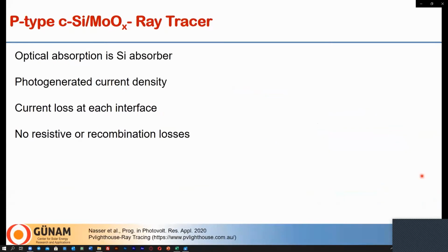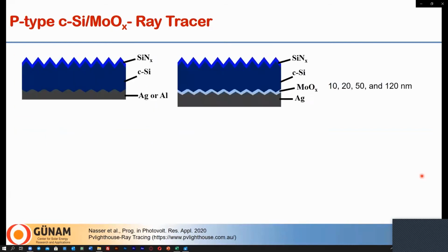So in order to further understand what happens at the rear side, we used the wafer ray tracer tool from PV Lighthouse. In this tool, it doesn't take into account any recombination or resistive losses of the layer or interfaces. It just predicts the maximum photo-generated current density that we can achieve from our device. And also it can predict how much current is being lost at each layer or interface of the solar cell. So here is the solar cell structure used in this simulation.